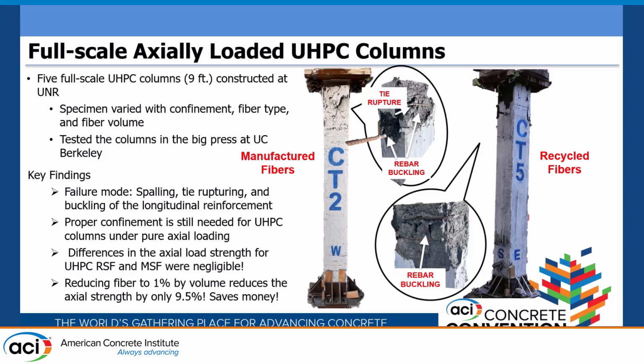So I guess we saw that the fibers aren't that crucial. We also saw that if we reduce the fiber volume by 1%, the axial strength drops by around 9.5%, but 9.5%, if you actually look at it for structural purposes, is not as much. So if we can actually get away with using 1% volume, we kind of save money, right?